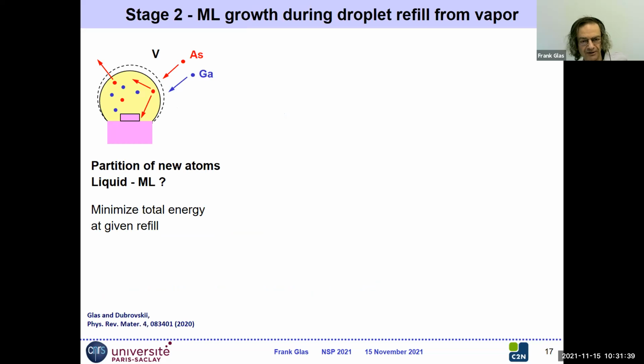So stage two now. If you remember, we have propagation of the monolayer, but we also have refill of the droplet from the vapor, because this one is definitely not instantaneous. So we input new arsenic atoms from the vapor. Of course, some will dissolve, but some will stay in the droplet. And the question which arises now is, of the new atoms that I put in the droplet, some might want to stay in the liquid to enrich the liquid, and some might want to join the monolayer to ensure the propagation of the monolayer.